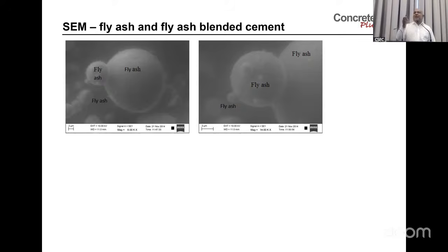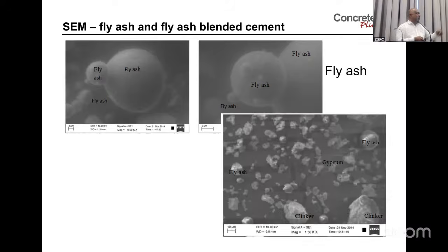Then there was an argument that at that time you were producing and promoting fly ash blended cement. Most of the engineers used to say that when you intertwine this fly ash in cement, it breaks. So it's a very good argument. Even at that time we checked it. Even in what you see in the bottom, you can see spherical particles. This is fly ash blended cement. Spherical particles are there, but I don't know exactly what percentage. But you can see reasonably spherical particles are there. So that's why it's promoted for working.